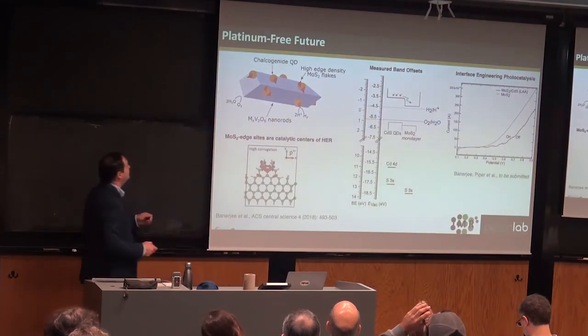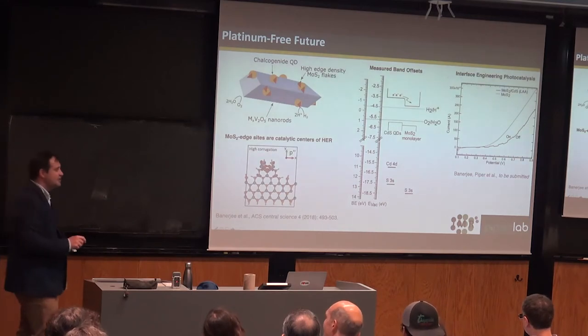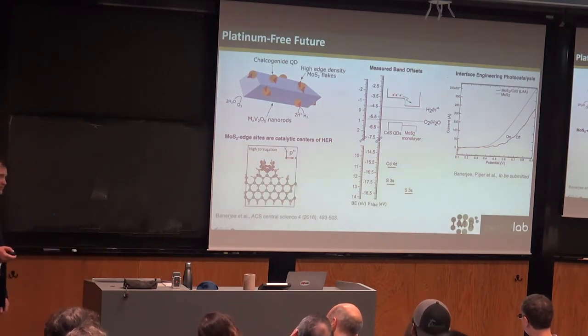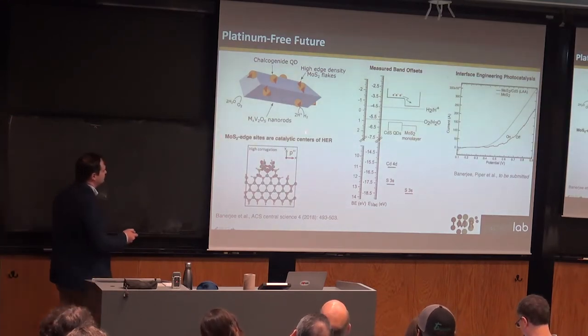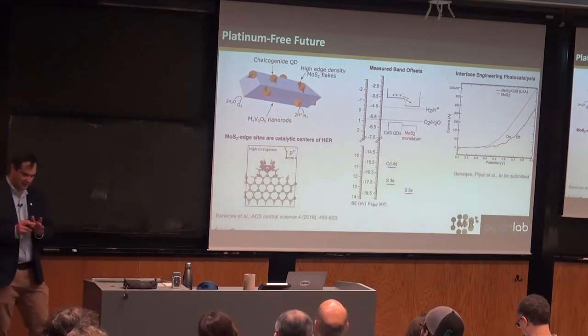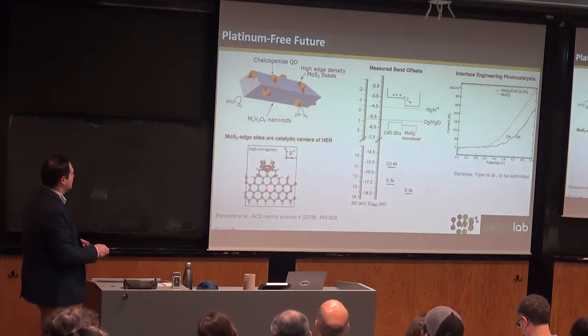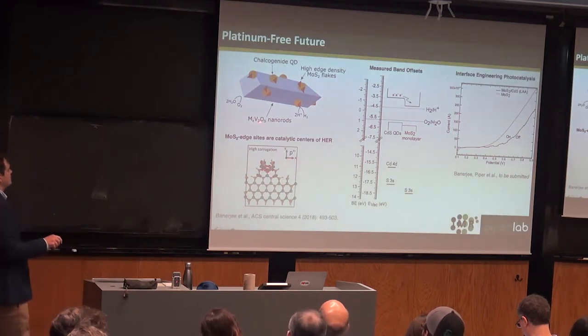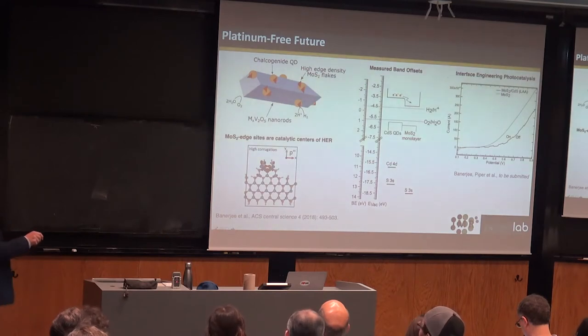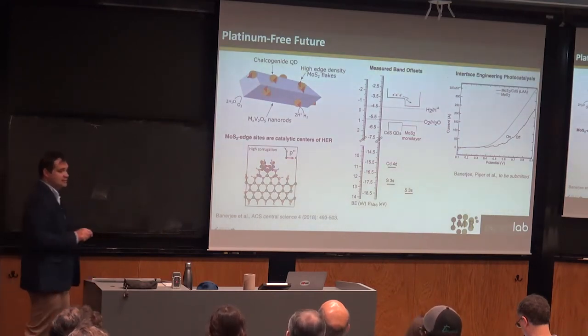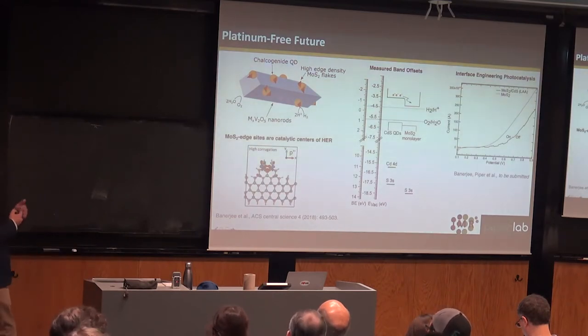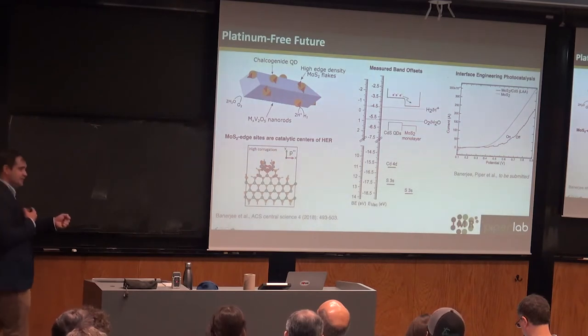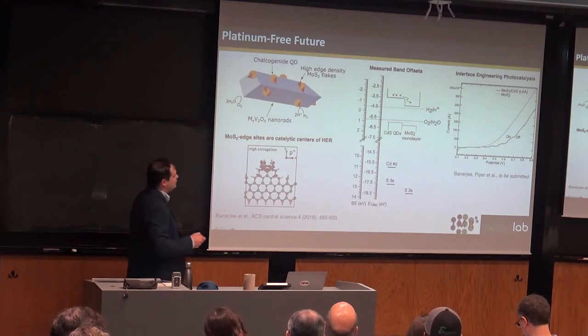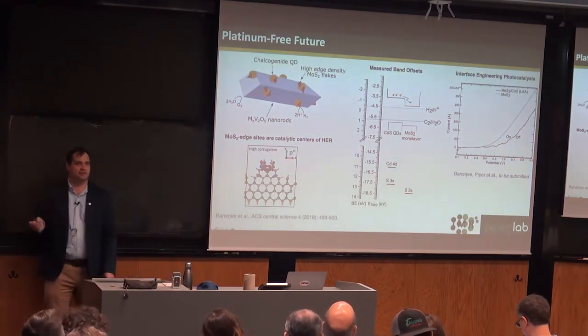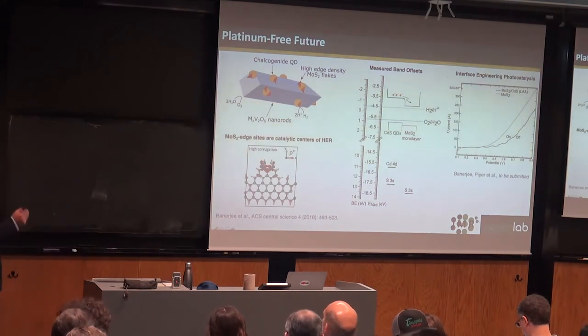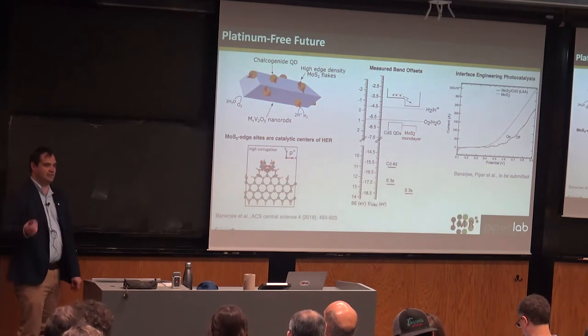But unlike Beyonce, I want a platinum-free future. So can we move away from platinum? One of the ideas is we could take advantage of molybdenum disulfide. If you've got corrugated moly disulfide flakes, the corners are really efficient sites for hydrogen evolving reaction. So instead of decorating your quantum dots with platinum nanoparticles, you can decorate them with moly disulfide flakes. The trick is, can you continue having the kind of charge separation you want in order to facilitate that? So again, it becomes an interface issue. With the interface, one of the things we found was the polarity is quite difficult to predict in the chemistry calculations. It became more useful to essentially ignore what the calculations of the interface were and just measure it.